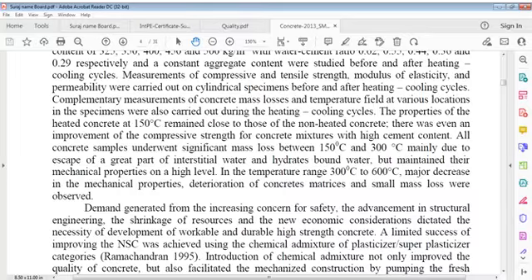Properties of concrete heated at 150 degrees Celsius remained close to those of non-heated concrete. There was even an improvement of compressive strength for concrete mixtures with high cement content. All concrete samples underwent significant mass loss between 150 degrees Celsius and 300 degrees Celsius, mainly due to escape of a great part of interstitial water and hydrates, bound water, but maintained their mechanical properties at a high level in the temperature range 300 to 600 degrees Celsius. Major decrease in mechanical properties came with deterioration of the concrete matrix.